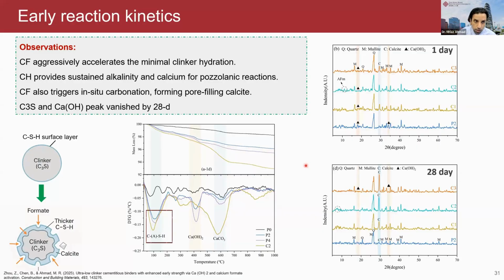because we also have slag, 20% slag here. We have calcium hydroxide. And we also have calcium formate. So by improving the hydration of the clinker, this system can also increase the reaction of these supplementary materials such as slag and fly ash, because there's a sufficient amount of calcium hydroxide available.